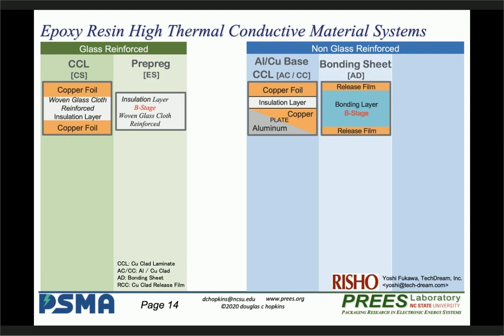Here's just the bonding layer, the B-stage material. This is partially cured epoxy. You can use it to bond together many layers. Think of it as just an epoxy glue, but it comes in a nice sheet form, uniform thicknesses, and also has very high voltage withstand capability and high thermal performance. So we can use these to be able to stack. And then what would we stack?